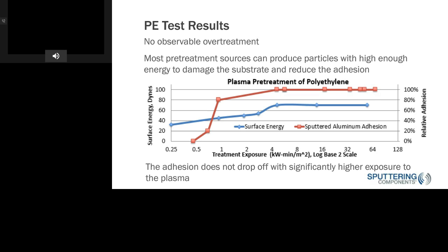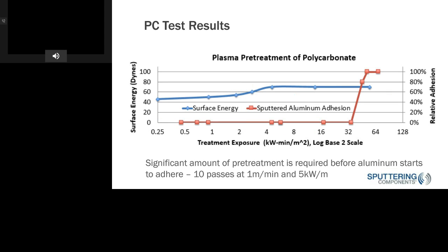Then we looked at polycarbonate. So this graph's for the pre-treatment of polycarbonate, the same X and Y axis here. And with polycarbonate, it really required a significant amount of pre-treatment before the aluminum starts to adhere. But we were able to see that, you can see the treatment exposure here was much more than with the polyethylene. So we ended up doing 10 passes at 1 meter a minute and 5 kilowatts per meter.